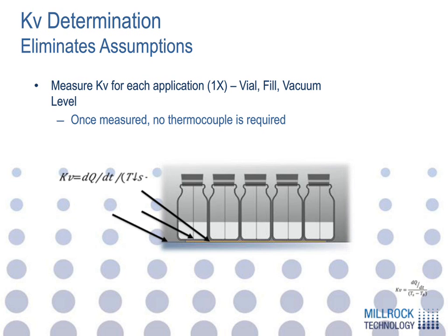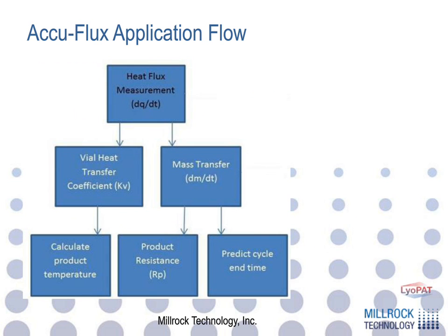One of the things we're also going to look at is Kv is considered a constant, and depending on how you're measuring that, you want to make sure that you're measuring Kv during the initial portion of the primary drying cycle. So if we can measure the heat flow going into the vials, we can also determine the thermal conductivity of the vial, the heat transfer coefficient. We can calculate the product temperature based on that. We can also calculate the mass transfer going on per vial and per batch, determine the product resistance, and ultimately predict the primary drying cycle time.